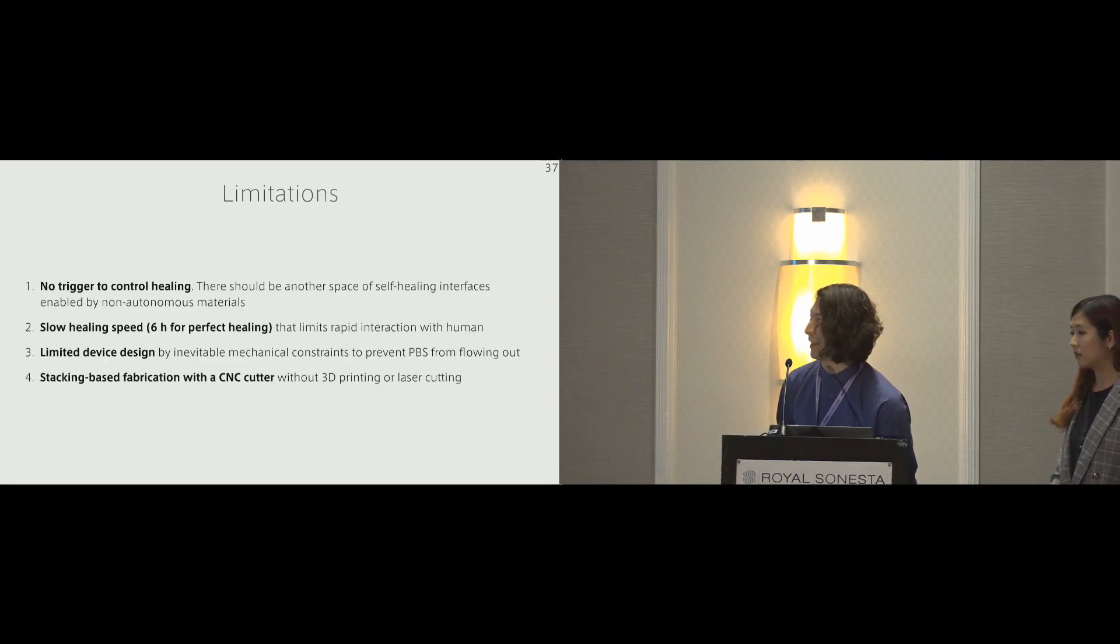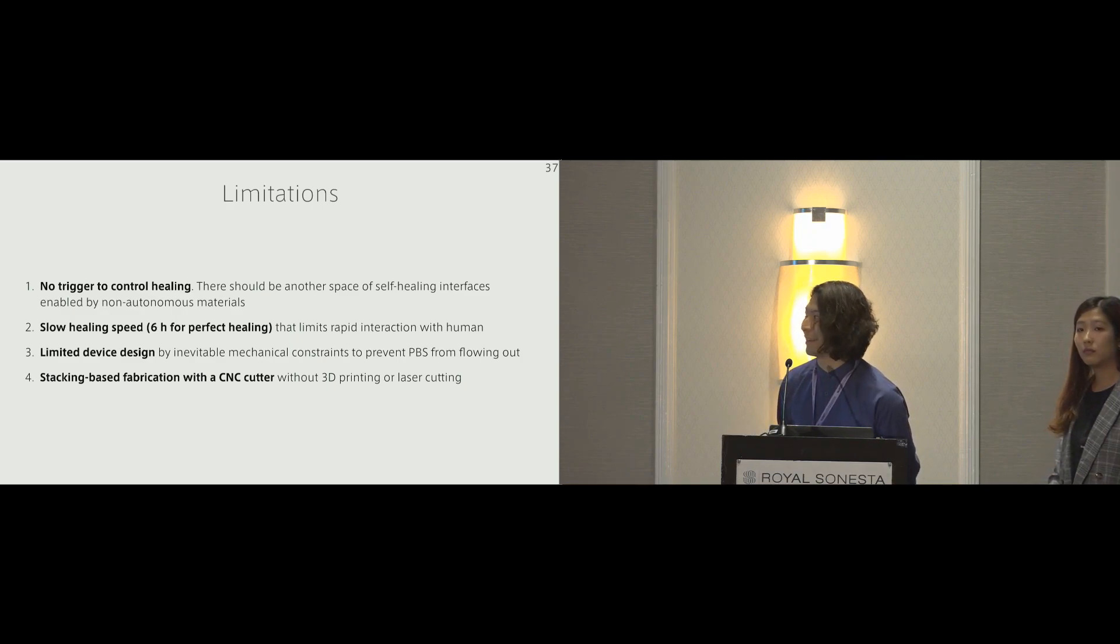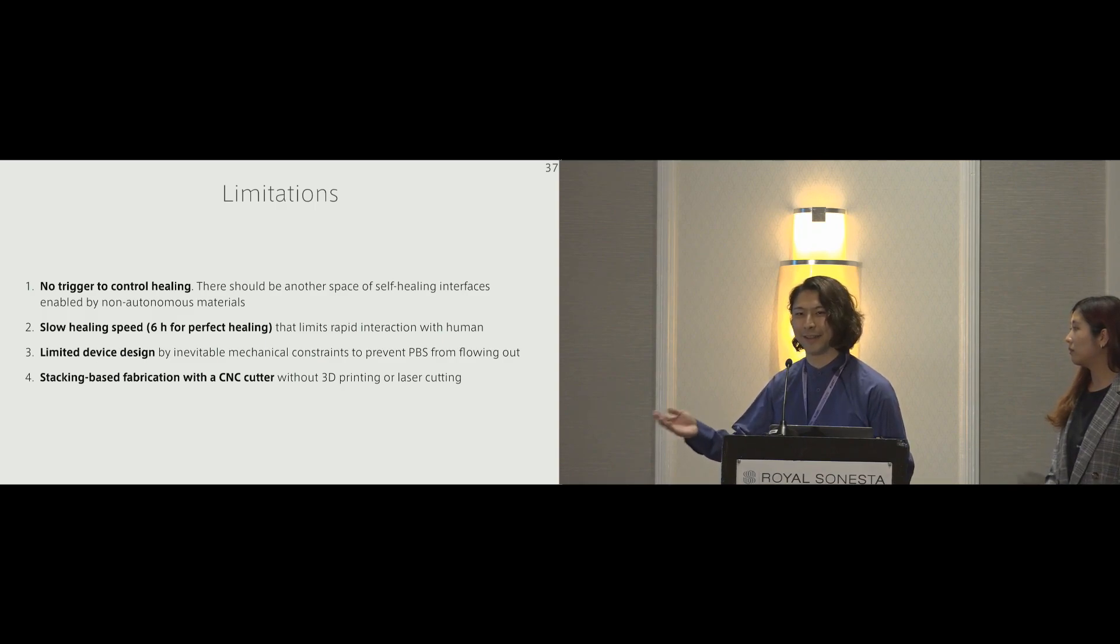There are some limitations to our project. First of all, there is no trigger to control the healing. There should be another design space if we have a self-healing material which has a kind of switch to turn on and turn off the self-healing property. The next limitation is the slow healing speed, so far six hours in our implementation. But if we just make the material sustain a certain amount of mechanical force, we don't have to wait until the perfect healing for six hours. We can just wait, for example, 10 minutes or so.